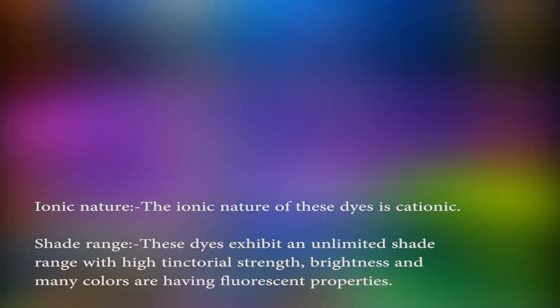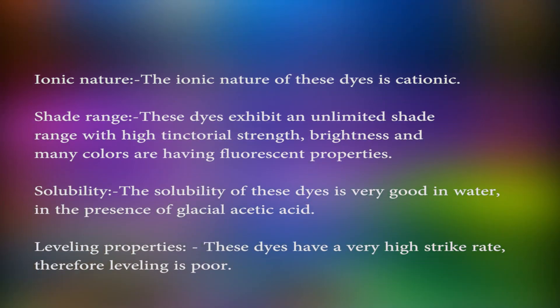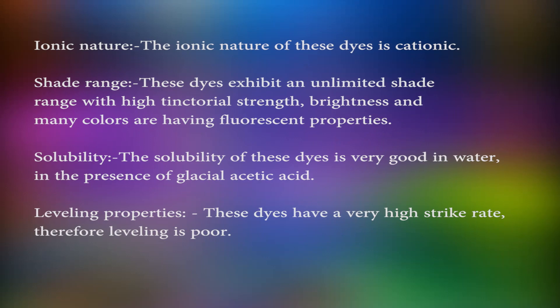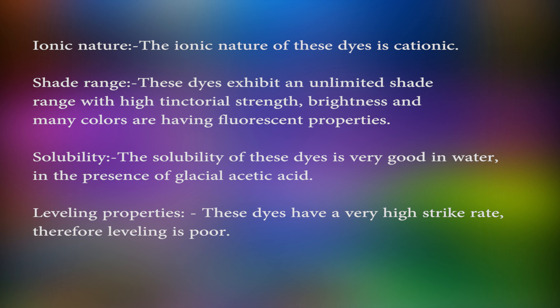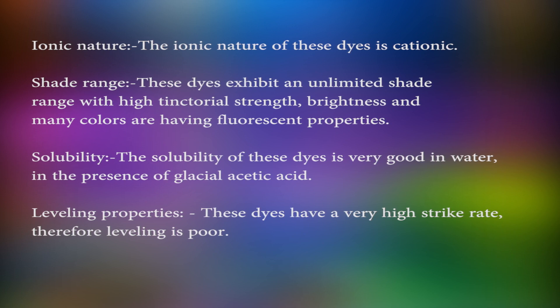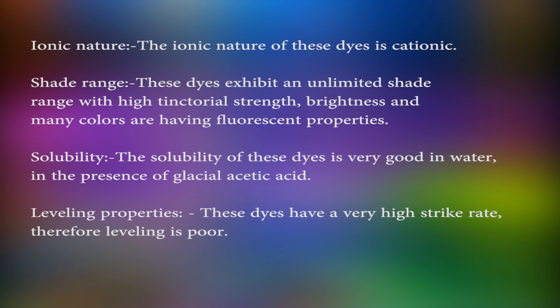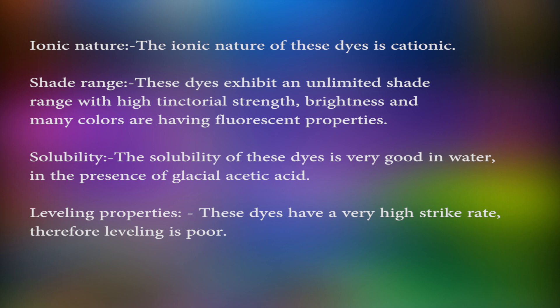Ionic nature: the ionic nature of these dyes is cationic. Shade range: these dyes exhibit an unlimited shade range with high tinctorial strength, brightness, and many colors have fluorescent properties. Solubility: the solubility of these dyes is very good in water in the presence of glacial acetic acid.